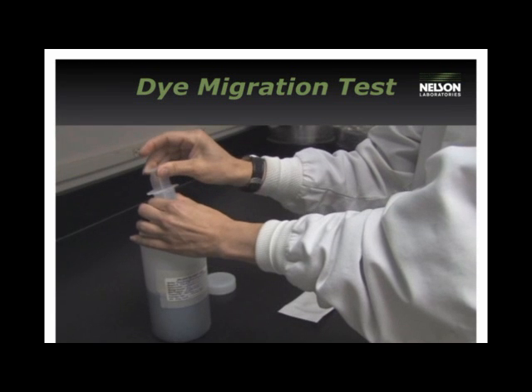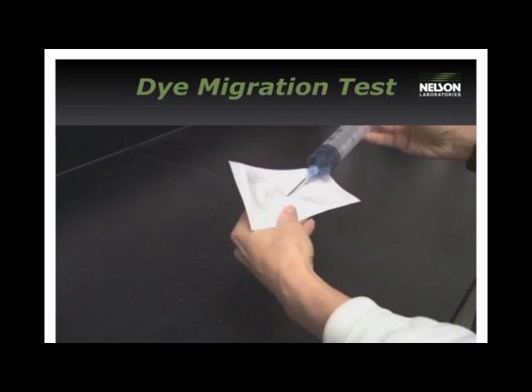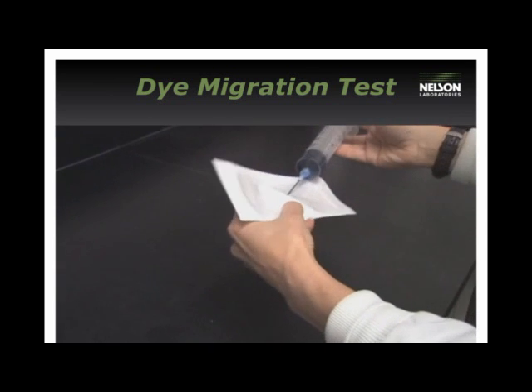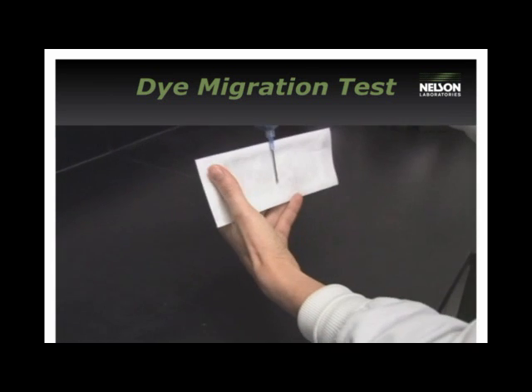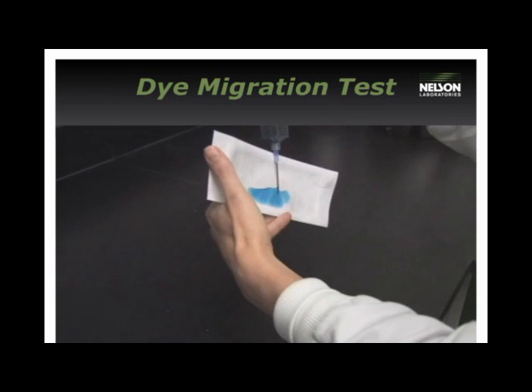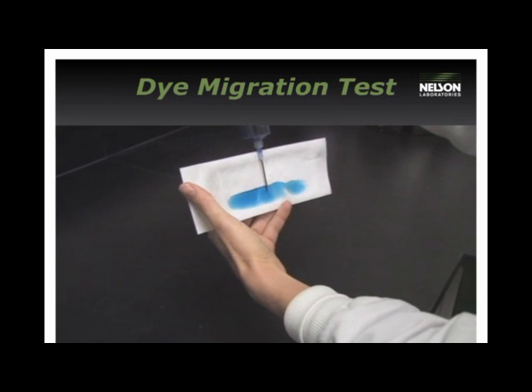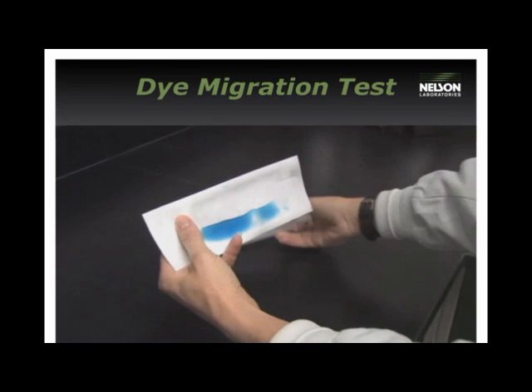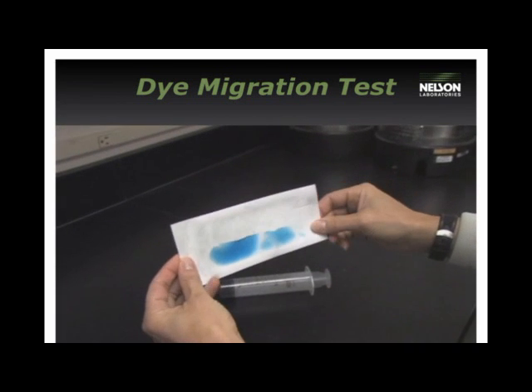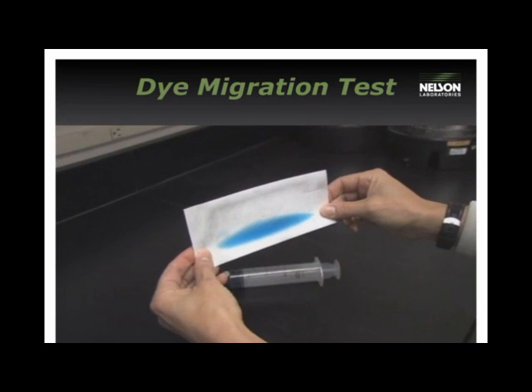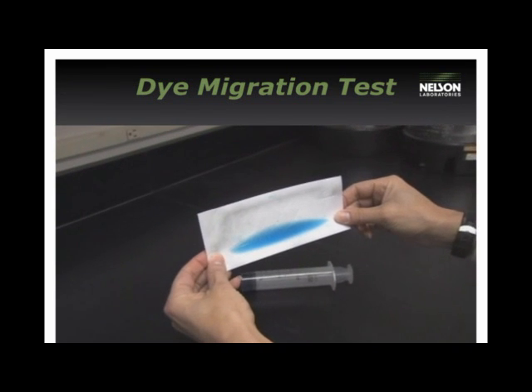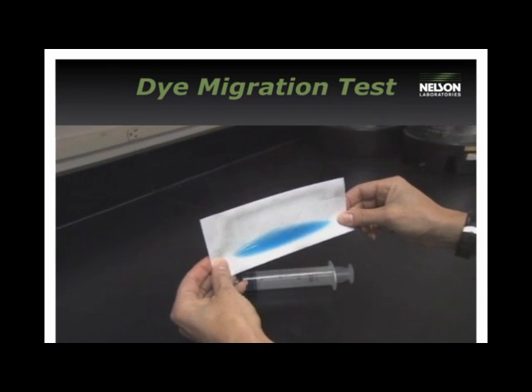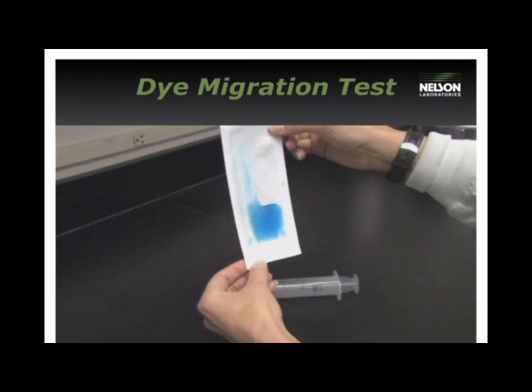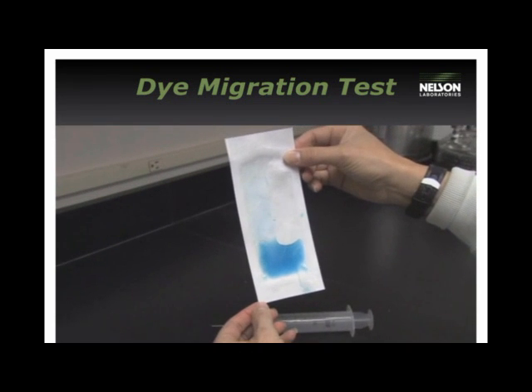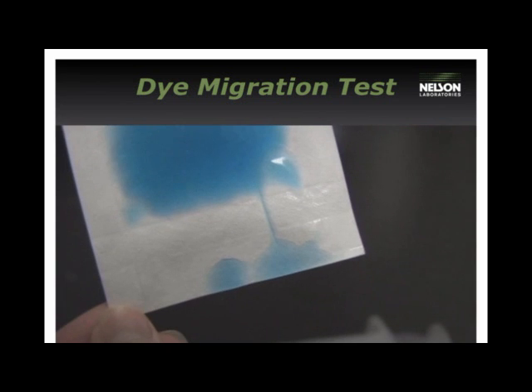Dye migration is a seal integrity test. A dye solution is injected into the center of the sterile barrier system using a needle and a syringe. The weight of the dye is maintained on the seal for 5 to 20 seconds. The sample is rotated and all sides are tested. If any dye leaks through the seal, the side is reported as a failure.